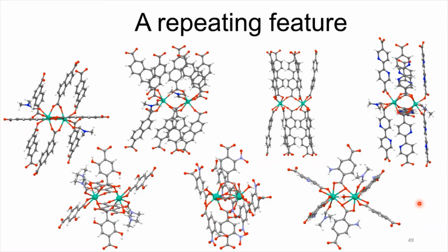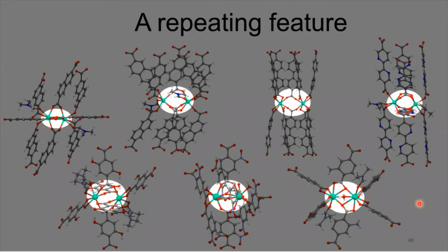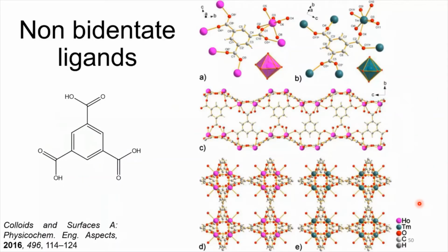But there was one thing in common, and I think I mentioned all of them, but in case you missed it, all of them have these dimers. So we thought the key for stabilizing and growing these materials may lie in the nature of that dimer cluster. And first I told my advisor, oh, it is because we're using terephthalic acid, it's just a bidentate ligand. What if we have 3 of them? And even in some of those, you can see that there's still dimers. It's just chains of dimers that go along. So what is the reason behind this?